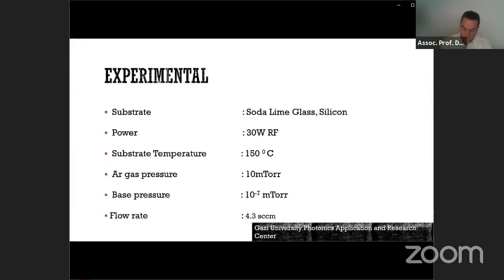In this process, the substrates are soda lime glass and silicon, power 30 watt RF, and substrate temperature 150 Celsius, argon gas pressure 10 millitorr, base pressure 10 to the power of -7 millitorr, flow rate 4.3 sccm.